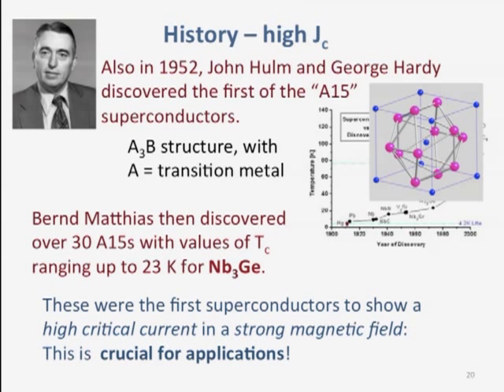But Bernd Matthias ran with this. And he discovered over 30 of these A15 compounds with TCs ranging up to 23 degrees. And my boss, Jack Wernick, was one of the guys that worked on this one. This is niobium-3 germanium. That's the highest TC.